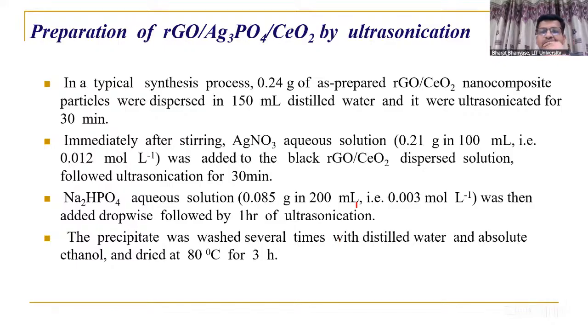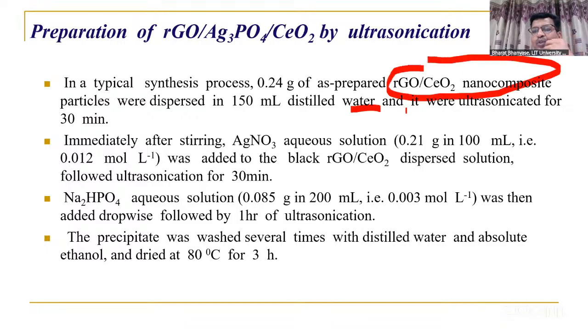Then we have loaded Ag3PO4 on that. The prepared rGO-CeO2 nanocomposite was dispersed into distilled water and sonicated for 30 minutes, then immediately AgNO3 solution was added. Then Na2HPO4 aqueous solution was added to this dispersion. This forms Ag3PO4, which gets loaded on the RgO-CeO2 nanocomposite, leading to formation of rGO, Ag3PO4 and CeO2 composite.